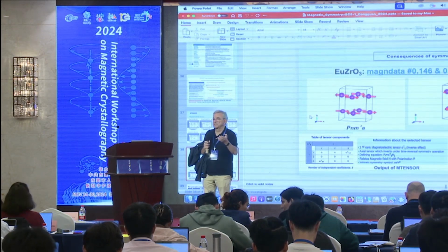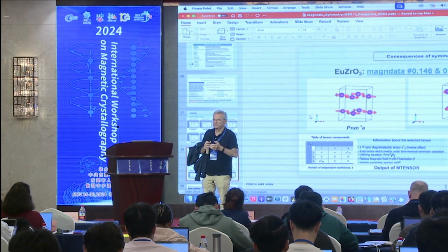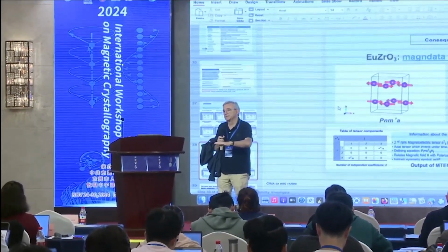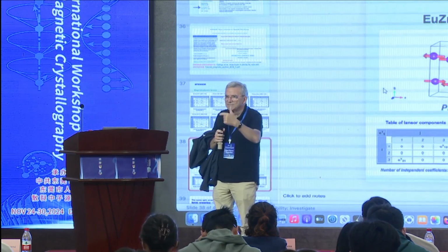But in many cases, for instance, if you are in a tetragonal structure and your spins are in the plane and are collinear in one direction, then you are losing the tetragonal operation necessarily. And then in your magnetic CIF file, the atoms which were related by the fourfold rotation will be split. But in principle, ISOCIF is a very nice tool of the ISOTROPY software.